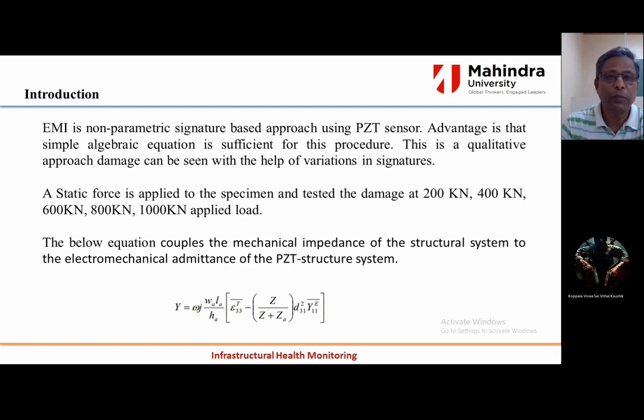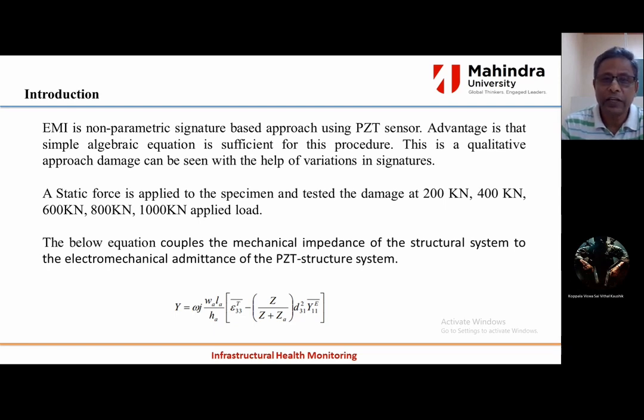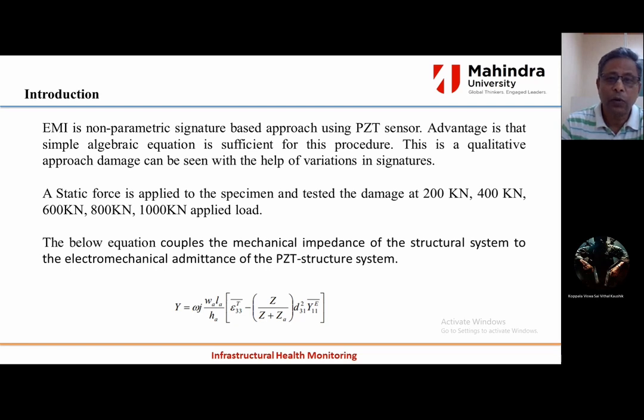EMI is a non-parametric signature-based approach using PZT sensors. An advantage is that a simple algebraic equation is sufficient for this procedure. With this easy qualitative approach, damage can be seen with the help of variations in signatures. The static force is applied to the specimen and tested for damage at 200 kN, 400 kN, 600 kN, 800 kN, and 1000 kN applied load.